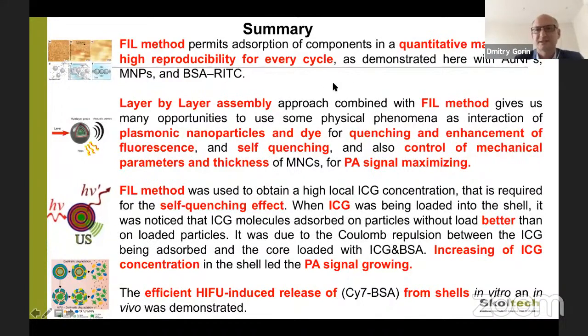I think I can demonstrate how we can prepare multimodal and multifunctional particles, and you can apply a really very easy and very reproducible technology. It's layer-by-layer assembly and the freezing-induced loading method, and we can combine both technologies for obtaining photoacoustic and fluorescence signals. And also we can use two phenomena for increasing or decreasing fluorescence and decreasing or increasing the photoacoustic signal. We also demonstrate the possibility of using high intensity focused ultrasound for release of encapsulated substances.